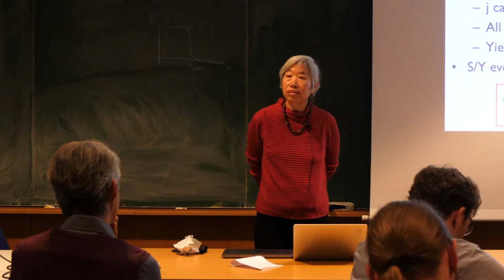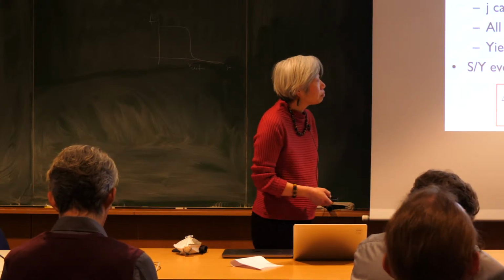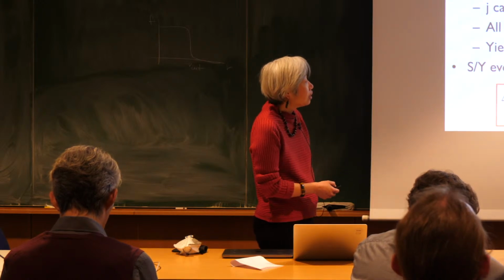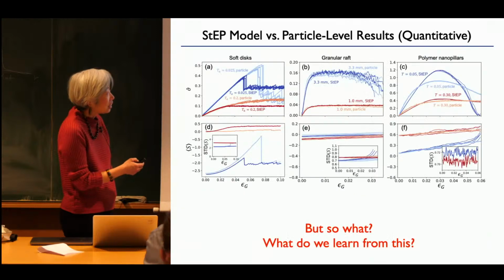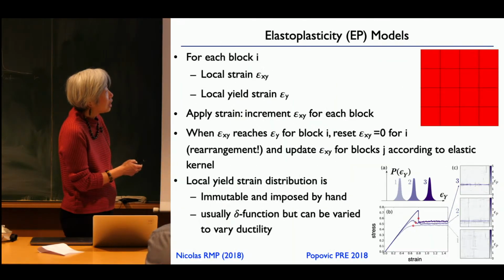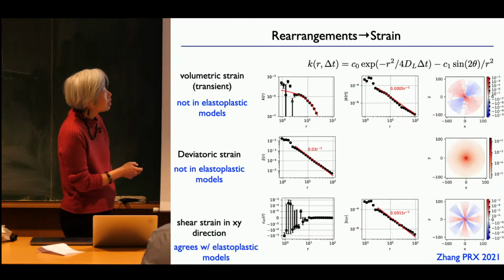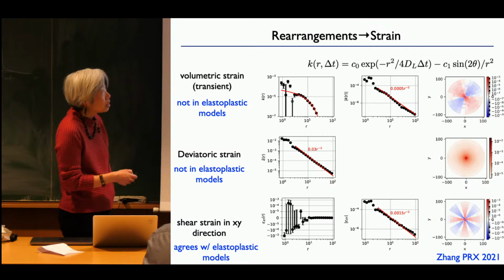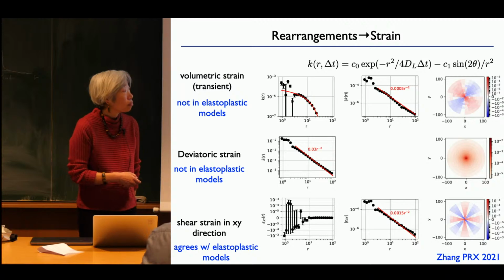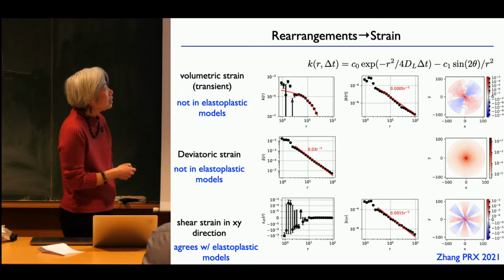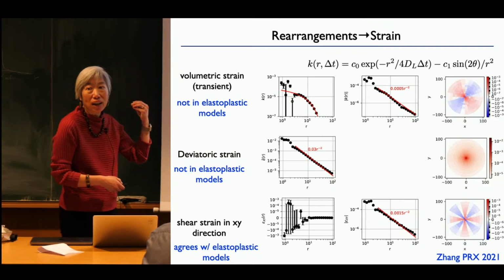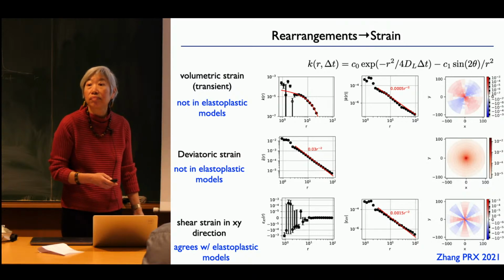So Andrea, maybe I missed it, but in your new step model, do you still use the long-range elastic interactions as in the previous versions, like the Eshelby kernel? Yes, so these are still present. Is that correct? Correct. It's that Eshelby kernel, but it's not exactly the Eshelby kernel. What we found was that, in fact, it was the deviatoric stress that was so important. So instead of doing this, we actually propagate that. You only do the middle row, is that right? Well, we update epsilon. This is just the magnitude of it. So we do have epsilon xy, but we also have epsilon xx minus epsilon yy. Okay. Because that's what's important.